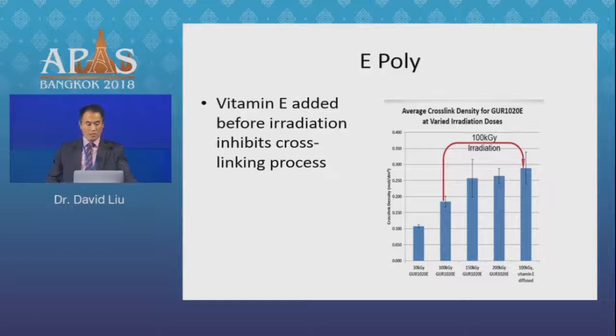But the theoretical advantage of diffusion over blending is that if you add the vitamin E to the poly prior to irradiation, it does seem to inhibit or make the cross-linking process a little bit less efficient. And so for the same radiation dose, you don't seem to get as high a cross-linking density. Now, whether this makes any clinical difference is yet to be ascertained, but that is one of the theoretical advantages of diffusion over blending.